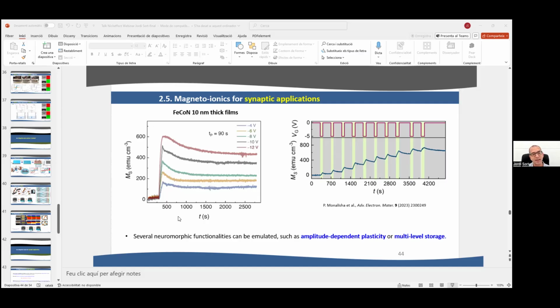We are doing, in this case, seconds. Just think that, for example, the solid state drives that you can buy in the shop and we use to store data have an endurance of 10 to the 4. So in that sense, our magnetoionic material is close to that value. There are other materials, with combined action of ferroelectric and magnetoionics using bismuth ferrite, that have shown even higher endurance, several 10 to the 4, even 10 to the 5, very close. Also, the group of Professor Beach at MIT, using proton magnetoionics, can do 10 to the 4 cycles. So that's a bit where we are now, state of the art.